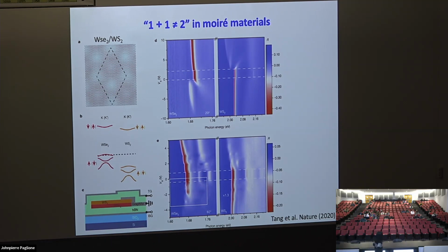So that second harmonic generation carries the symmetry of your crystal. So it will know the armchair or zigzag direction of your crystal. So you first do second harmonic on each crystal. You find out which one is armchair, which is zigzag, and then you put the two together. That's how we stack them with a target angle, at least, and which could be very accurate, you know, half a degree-ish.